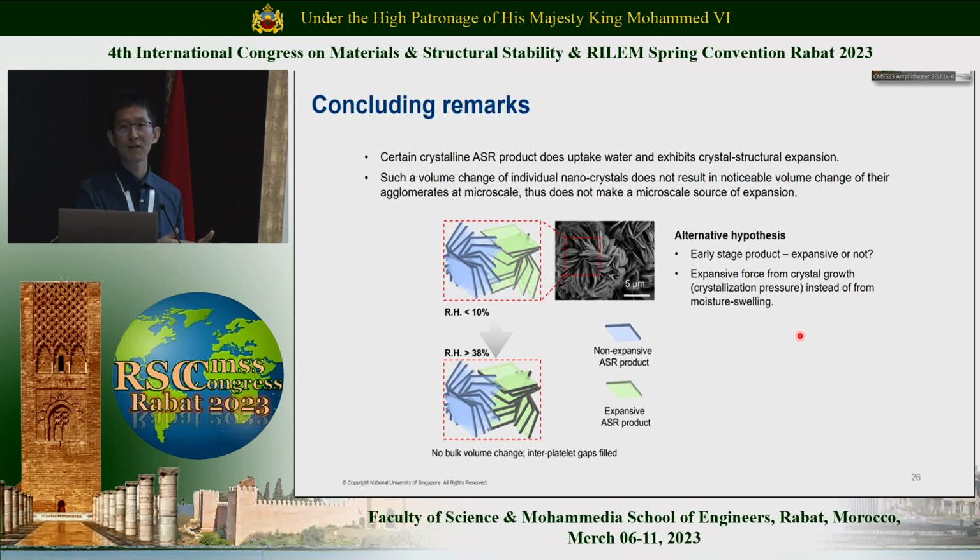It might happen at a very early age due to an earlier form of the ASR product, which might have a different response to the moisture change. Or maybe it's rather because of the crystallization pressure, so the growing of the crystals opens up the crack, instead of the swelling of the crystals causing the opening of the crack.